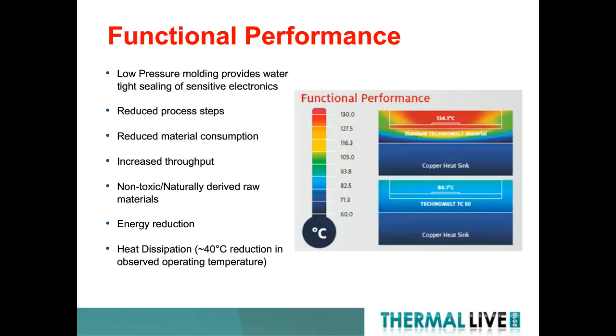So in the top of that depiction on the right, what you see is a power device mounted on a board and then molded with the Technomelt material. It's placed against a heat sink to direct the heat from that power device out into the material itself, and we've measured the temperature in this model in both situations. What we saw is about a 40 C reduction in the observed operating temperature between these two situations.